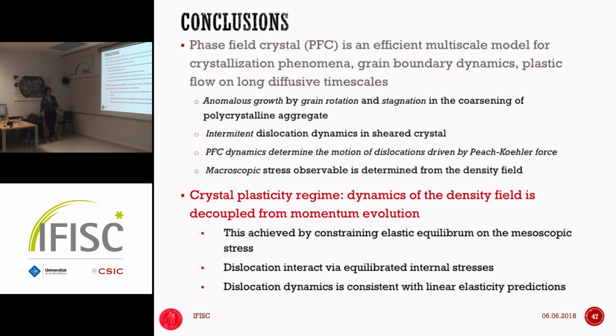And we have shown that in this framework in which we define defects as topological defects in the order parameter, we can calculate their motion, we can determine their location, and we can also constrain the interactions between them to be mediated by a stress that is maintained at equilibrium.